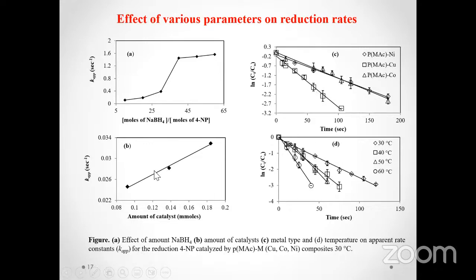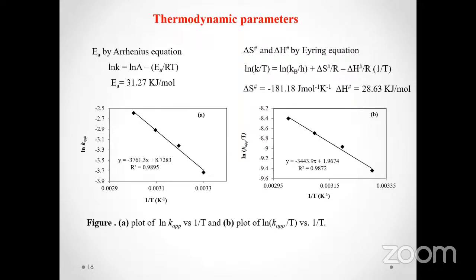And this system was also temperature responsive up to some extent, and by increasing the temperature of the reaction medium, the catalytic activity of the system, or rate of the reaction, was also increased. Similarly, we calculated some thermodynamic parameters by applying the Arrhenius equation and the Eyring equation, because whenever we observe a reaction, these thermodynamic parameters are also very important: the kinetic activation energy, the enthalpy change, and the entropy change during this reaction.